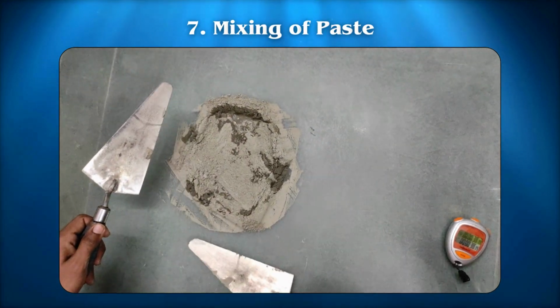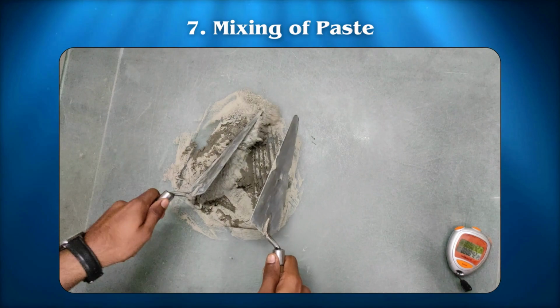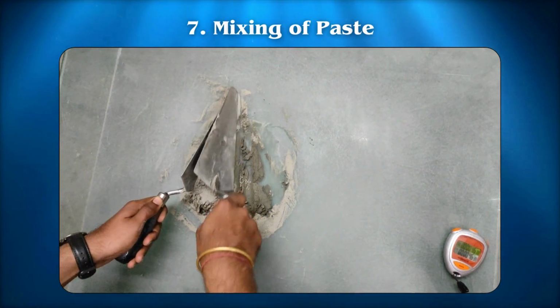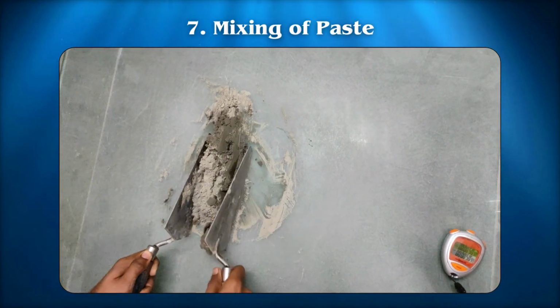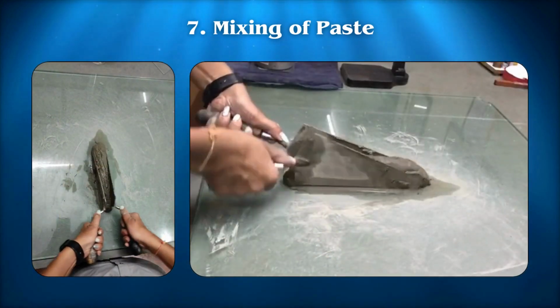Keep a close eye on the clock during the mixing process. Ensure that the time between adding water to the dry cement and commencing the filling of the mold falls between 3 to 5 minutes.